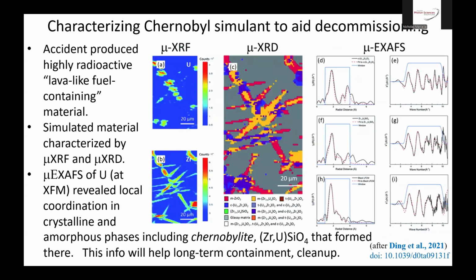Coming back to Earth, a group that collaborated with Ryan looked at simulated material related to the Chernobyl nuclear accident. In that meltdown situation, the nuclear fuel, the zirconium cladding, and the concrete containment all melted into a lava-like, highly radioactive material. So this group simulated that material and characterized it by microfluorescence, micro X-ray diffraction, and micro XAFS, so that they identified different phases that formed within it, both crystalline and amorphous. And they used the XAFS to reveal local coordination of uranium in both the crystalline and the amorphous phases in this material to help understand its stability and its properties for long-term containment and eventual cleanup.